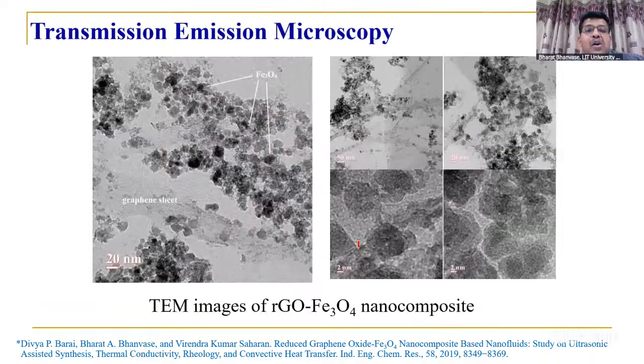So this is transmission electron microscopy. Already we have seen this is 20 nanometer size, and you can see these graphene sheets, well dispersed, and then we are loading some nanoparticles, that is Fe3O4 nanoparticles, nicely deposited on this material.